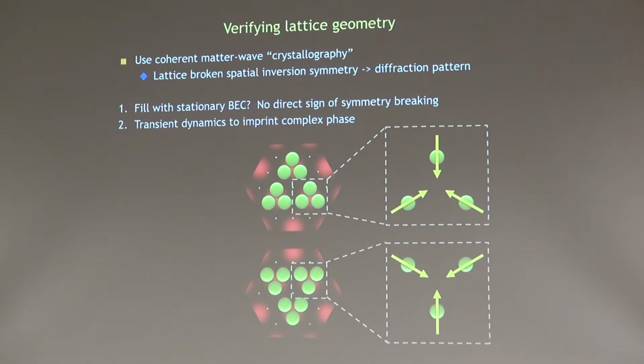So now within this infrared lattice, let's say we have a superfluid with amplitude on these 3 sites of the plaquette. These upward pointing triangles will now rush inwards. The population in them will rush inwards from the potential bowl that's introduced by the infrared lattice. And that produces a pattern of currents within the atomic distribution. And that is something that we can see in momentum space quite clearly. And we can see that this pattern of currents is different in one trimerization of the lattice than another.